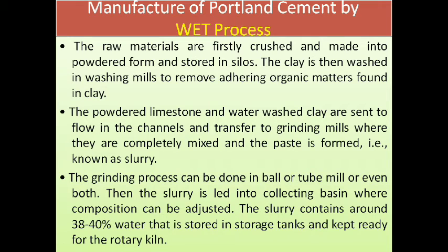In this wet process, which is preferred when the raw materials, limestone, clay, shells are present, the limestone is crushed to suitable size particles by a suitable mill. The soft clay is washed with water in a washing mill to remove the soluble and foreign materials. The clay is mixed with water to form a slurry. The powdered limestone is then mixed with a calculated quantity of clay slurry in a special ball mill for the wet process. The resulting slurry contains 40% of water. This slurry then goes to a correction tank for correction of composition.